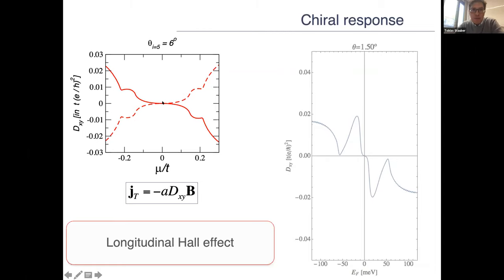All right, so there seems to be a clear correlation between the chirality of the underlying atomic system and the electronic system. This means that if you switch the twist angle from plus 6 degrees to minus 6 degrees, you just swap these curves. This was reasonably to be expected, but interestingly, across the magic angle there will be a sign change, a change in chirality, which is now decoupling the underlying crystallographic chirality from the electronic one.